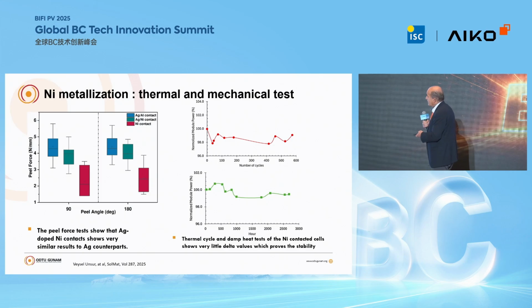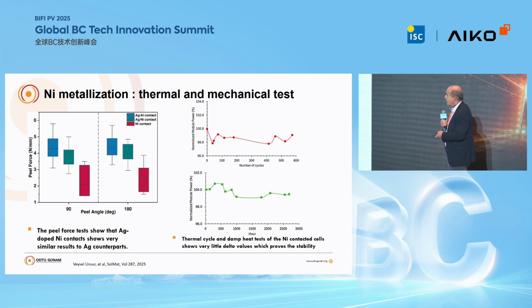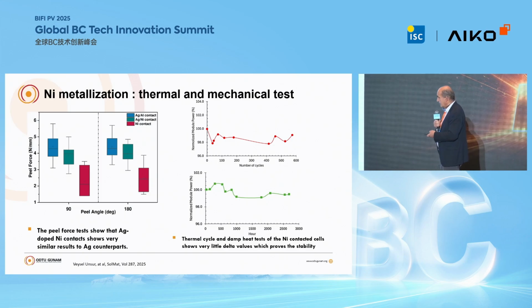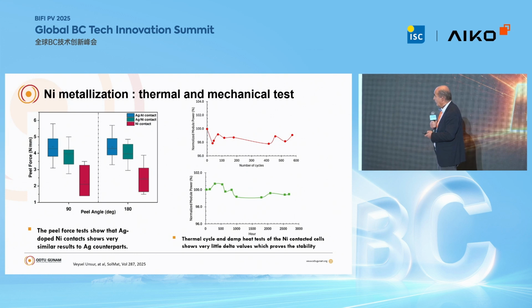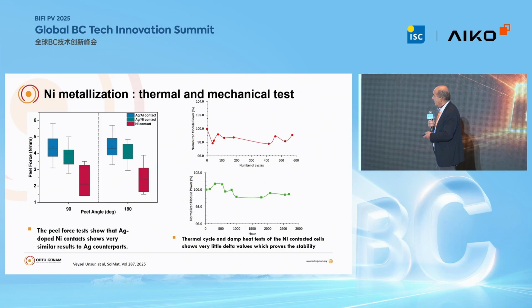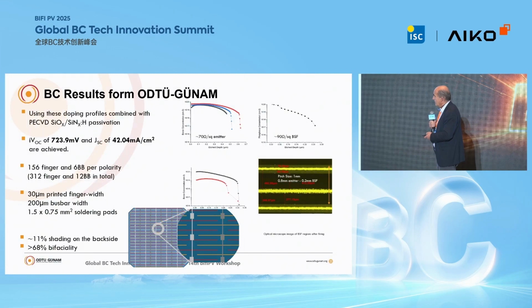We did a couple of studies like peel force, thermal cycle and damp heat tests, and they are all good. The contact is behaving quite well in these tests.